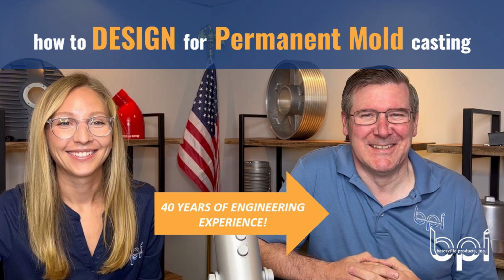When we go across a parting line, though, there can be a slight amount of mismatch at that parting line. The machining has to be done in separate operations, so that's where those concentricity issues develop from the mold itself. The castings will do exactly what the mold does. So when it goes across a parting line, the tolerances require a little more ease. Yep, you need a little bit more room in your tolerances to accommodate the features across the parting line. Okay, good.